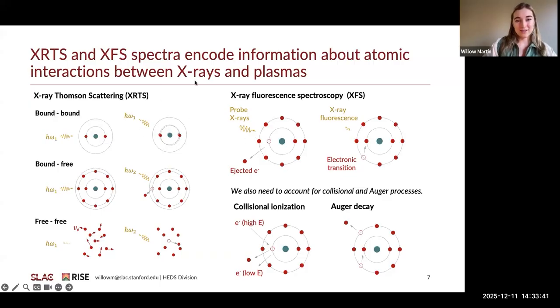On the right-hand side, we have a diagram for fluorescence spectroscopy, which I've argued can also serve as a temperature diagnostic, but there is more model dependency built in there. In order to calculate fluorescence spectra, you really need a detailed atomic model, and you need to calculate the rate equation, which would tell you how ionized you expect your plasma to be under certain plasma conditions. So given a temperature and a density, you can calculate with a detailed atomic model and atomic kinetics modeling what your expected degree of ionization is, and therefore what energy you expect your fluorescence feature to appear at. You can stop me and ask a question there if you.